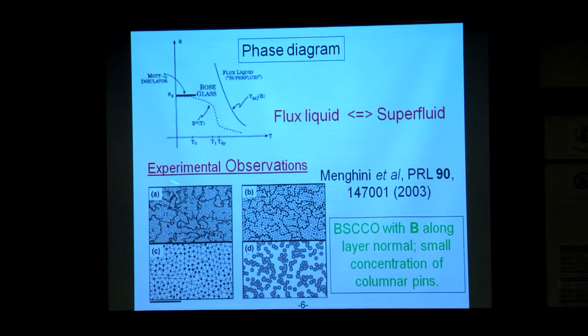And what one finds is that the Bose glass phase with columnar pinning basically has a polycrystalline structure. There are regions where the vortices form a nice crystalline lattice, like the Abrikosov lattice, but because of the pinning, the disorder, this Abrikosov lattice breaks up, and one basically has a polycrystalline structure with grain boundaries. So this is what is known experimentally.